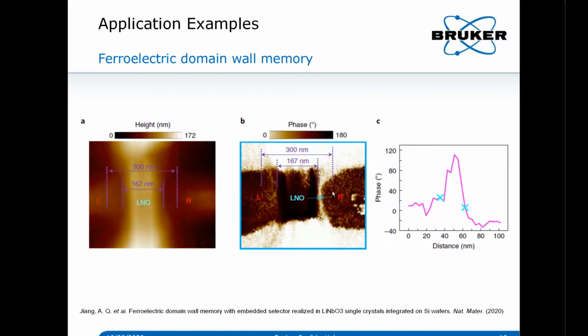For normal AFM tips, the tip radius can be as sharp as a couple of nanometers. But we previously mentioned that for PFM, you always need a conductive tip, and the tip radius will be bigger because of the conductive coatings. So here you can see the lateral resolution is about 10 nanometers, which is just limited by the tip radius. It's hard to imagine with other techniques you can really resolve this kind of fine features with this kind of lateral dimensions.